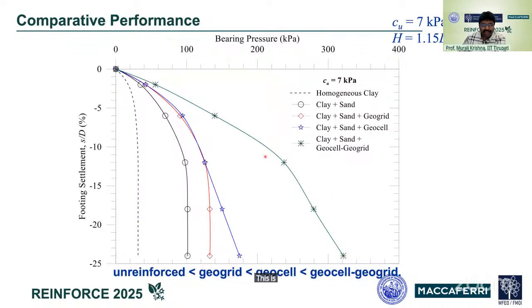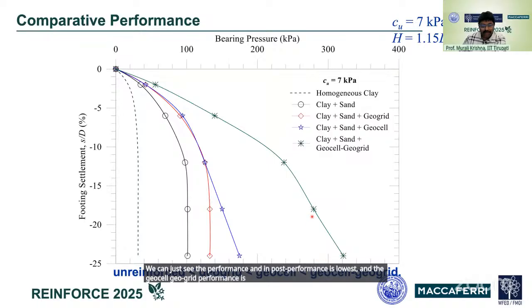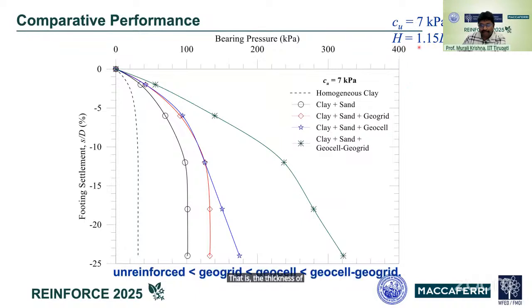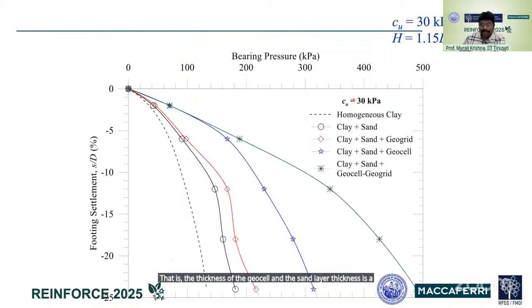This is for the case of the very soft clay, what we can see, what's the improvement. We can see the unreinforced performance is lowest, and the geocell geogrid performance is the highest level of improvement that could be obtained. These particular results are presented for H, that is the thickness of the geocell, and the sand layer thickness is 1.15D has been considered.